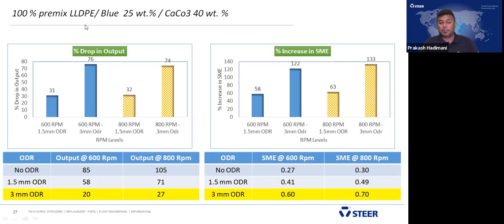When you talk about the 100% premix of blue pigment with a combination of calcium carbonate, with no OD reduction, we are getting 85 kg per hour at 600 RPM and 105 kg per hour at 800 RPM. After reducing the OD by 1.5 millimeter, 0.75 per side, we are getting 58 kg and 71 kg respectively. With 3 millimeter OD reduction, 1.5 millimeter per side, it's 20 kg per hour and 27. That shows the efficiency dropped drastically, because we have done OD reduction even on the conveying elements also, so it reduced drastically.